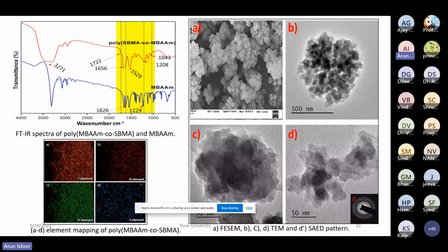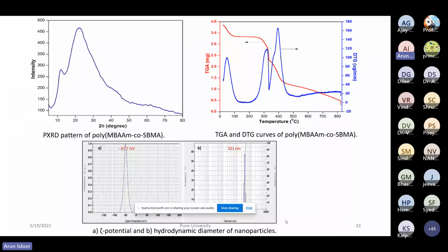Then after that, the TGA, the thermal properties, and also the XRD pattern indicated these particles are somewhat crystalline in nature. And then of course their particle sizing and the zeta potential were also measured. The zeta potential value was found to be about minus 47.7 millivolts.